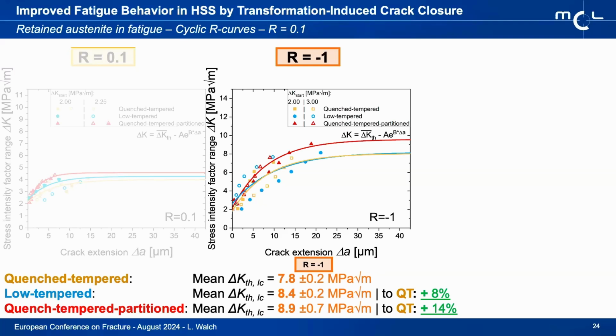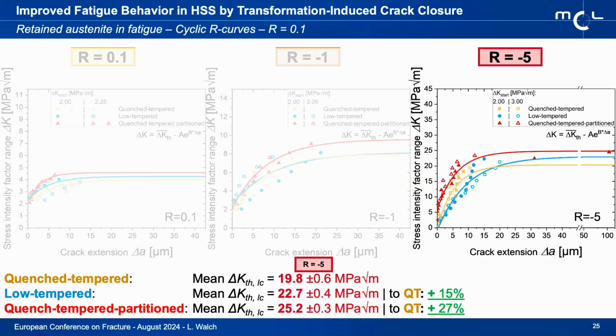If we look at the other fatigue test results at the stress ratios with a compression part, you can see that the trend actually holds and even increases, so that we have really a significant increase, especially in the long crack threshold at R equals -5 testing for the quench tempered and partition material state, but also for the low tempered partition material state. This is particularly important to note because for high-strength steels, that particular stress ratio is actually the one that's most application relevant. So quite a nice and encouraging result.